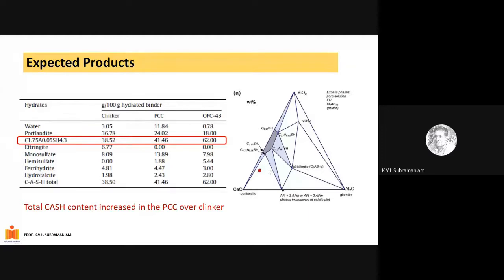So by playing around with the different compositions, we found that for the Portland composite cement, which is shown in the middle column here, PCC, we were able to produce about 41% of this calcium aluminosilicate hydrate, which is basically the CSH that is required to be produced.